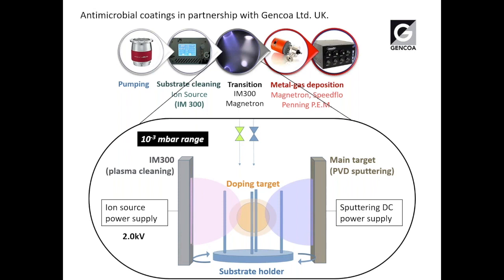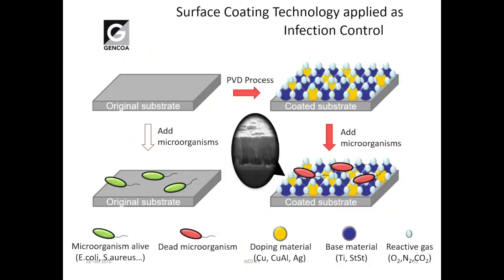The killing mechanism is not like copper or silver, by transmission of ions through a cell wall and DNA destruction. The antimicrobial effect is really quite exciting. We still have to do the physics, the biophysics, to find out the exact mechanism, but what we believe is happening is that we have nanostructured the surface, and physics and Maxwell's laws tell us that when we do this, we change the electrostatic environment of that surface.